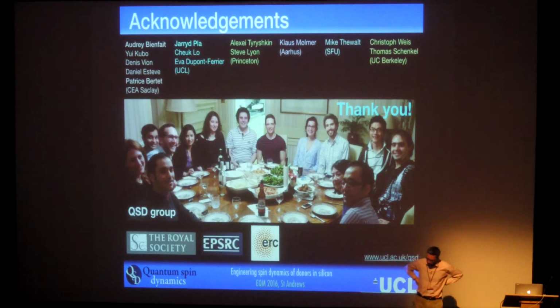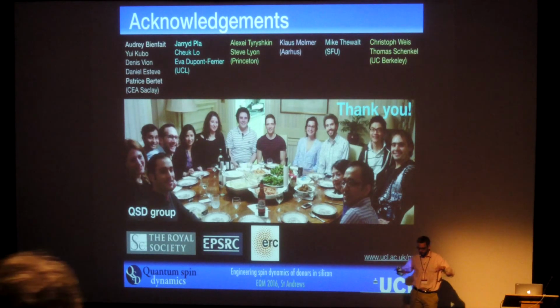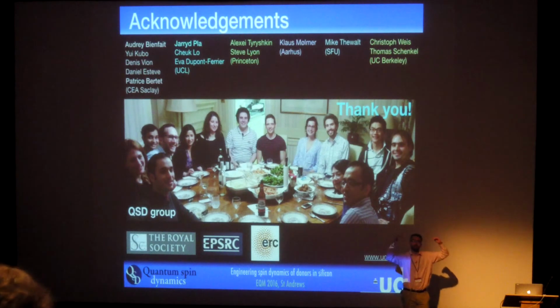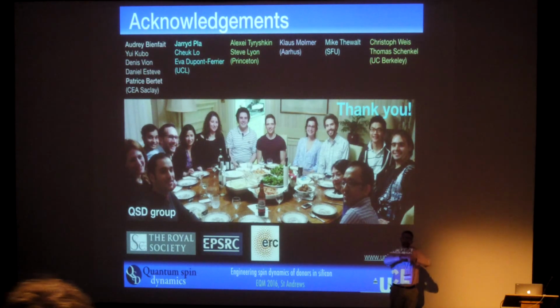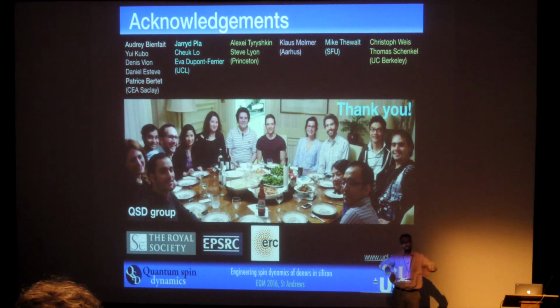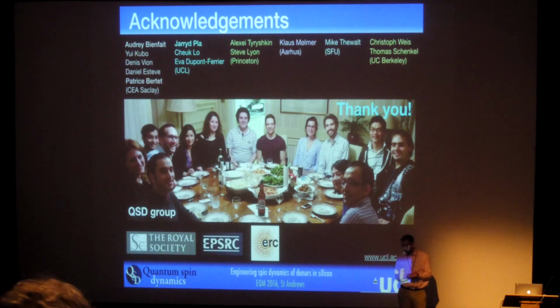Yes, so in this work, I guess the critical parameters would be how close they are to the surface, because that determines how closely they're coupled to the resonator, and that we can tune using the implantation energy. For the work with superconducting resonators, these bismuth dopants were implanted, and then you can choose the dose that will give you the concentration of dopants, and you can choose an implantation energy. So at that level, that's quite tunable.